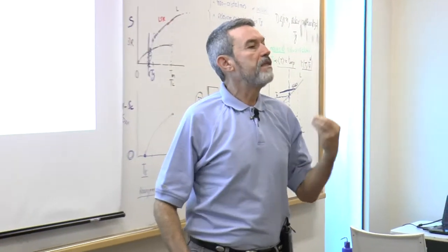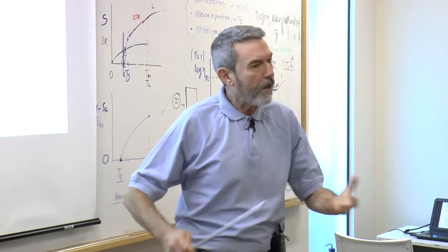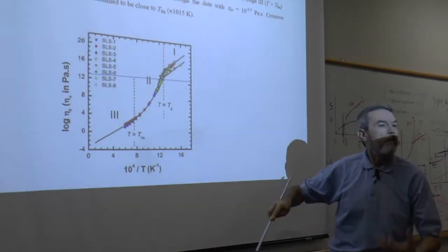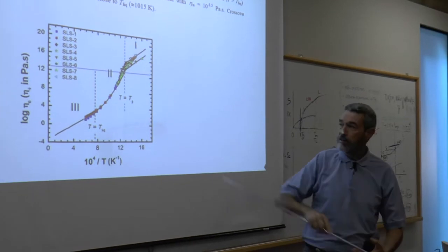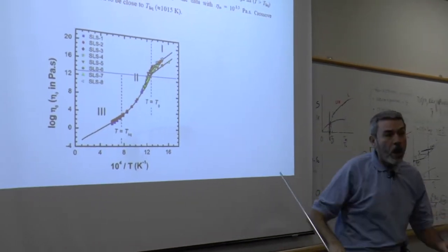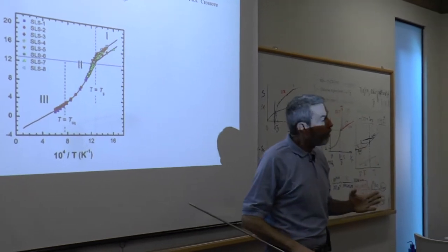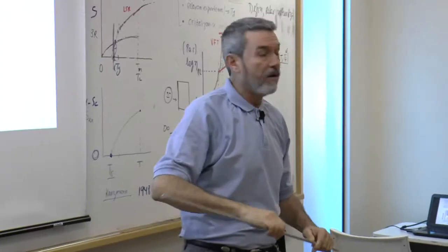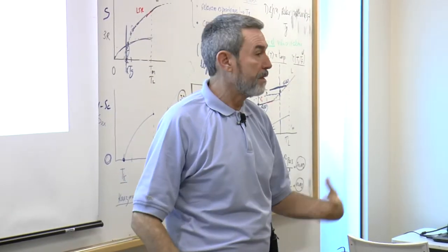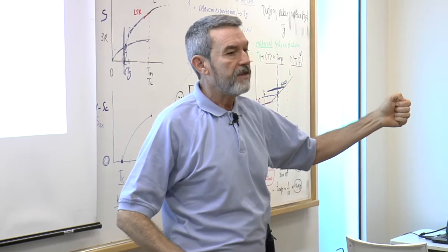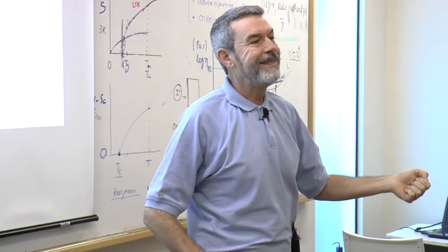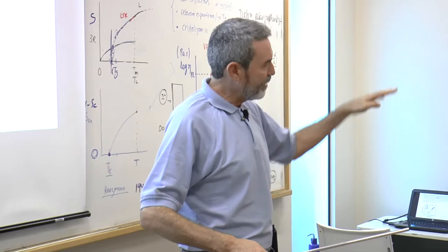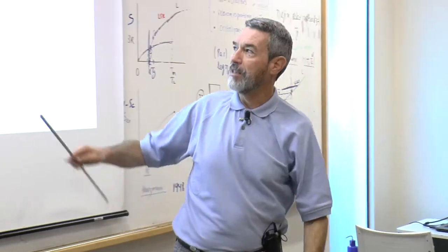Isostructural viscosity. To be rigorous, the structure freezes at Tf. But for practical purposes, in laboratory time scales, for practical glasses, Tg and Tf are not so different. But if you want to be rigorous, they are different, as I have shown in the previous slide. If you compare a fiber with a normal cooled glass, they have completely different TFs. Now, if you measure the TGs of these two glasses with the same heating rate, then they will show more or less the same TG, because they will relax and will reach the same state.